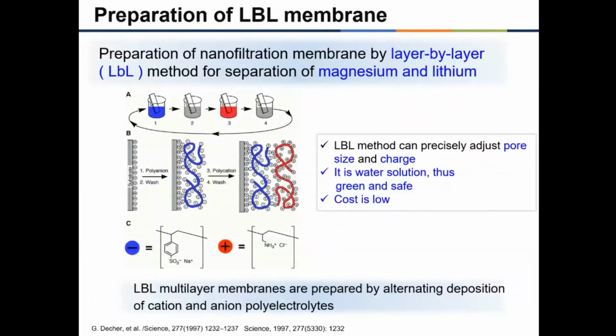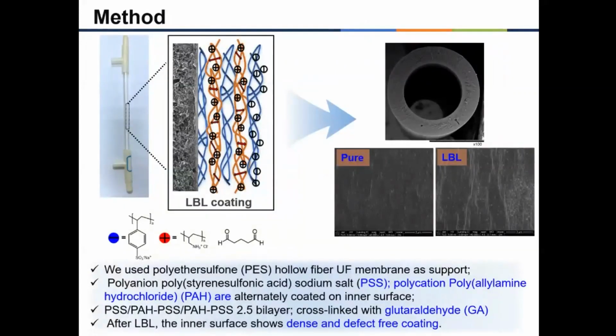LBL multilayer membranes are prepared by alternating deposition of cationic and anionic polyelectrolytes. The LBL method can precisely adjust the pore size and charge. It uses a water solution, thus green and safe. Cost is low. So we use the PES hollow fiber ultrafiltration membrane as support. We use PSS as polyanion and PAH as polycation. Their alternately coated layer has 2.5 bilayers, and it was cross-linked with GA.